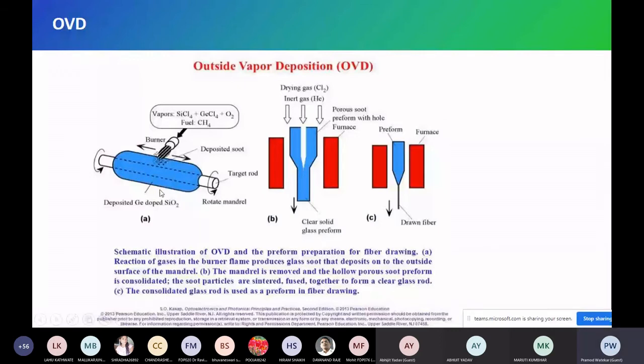We take a mandrel, okay, graphite mandrel or something. Sometimes we can take a glass mandrel, and we have to remove that mandrel afterwards. So you take that mandrel. This central one is the mandrel, this target rod. We say target rod, and over this we deposit the chemicals. So SiO2, GeO2, whatever we need, we deposit above this mandrel, and this mandrel is removed. So this is going to make the glass for you.